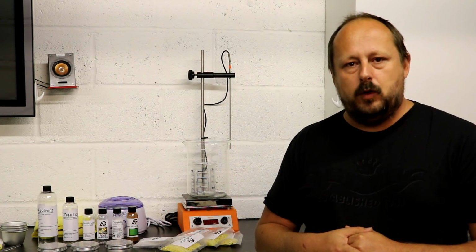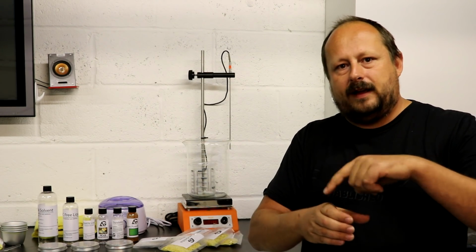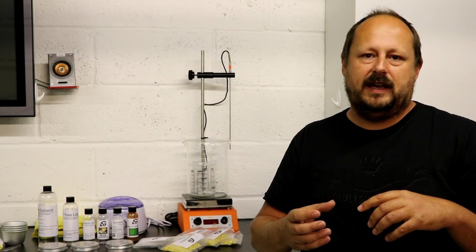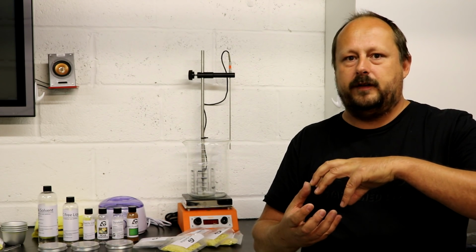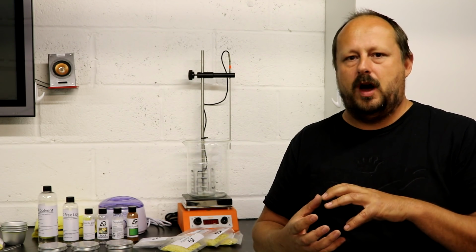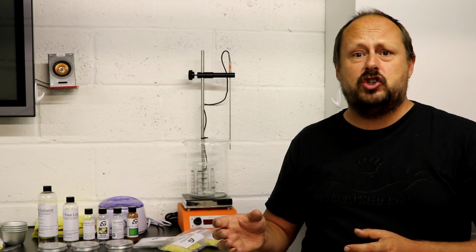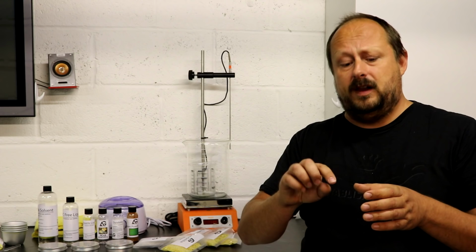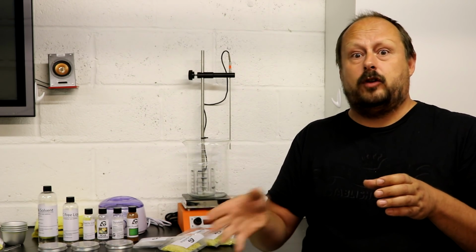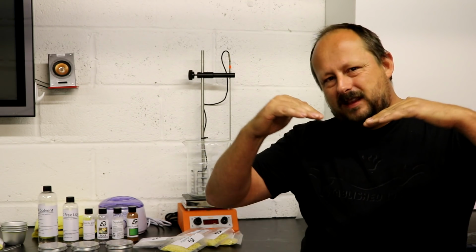Now you can prime your wax tins first, pour a tiny bit in there and rub it round so that wax covers the base, which is a good technique. It can avoid the wax separating from the tin. It shouldn't do that anyway, but if you're doing a hard wax, it can. So you could prime your tins if you like. You could also do staggered pours, so you could pour a little bit in after you've primed it and that's solidified, just a thin layer, and then when that's cooled you put another layer on, and that stops the wax collapsing in the middle, okay?